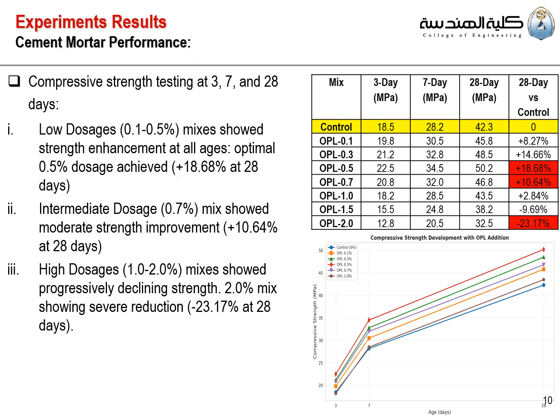The high dosages from 1 to 2% OPL mixes show progressively declining strength, where we have a severe reduction in the compressive strength, up to negative 23.17% at the 28th day.